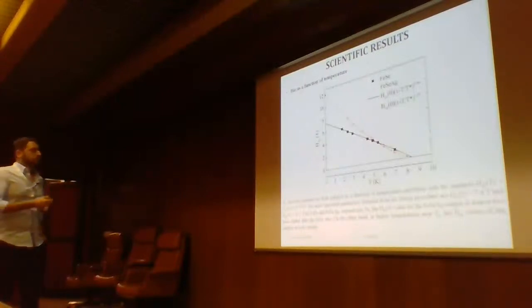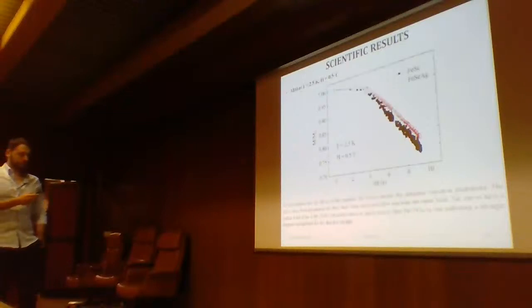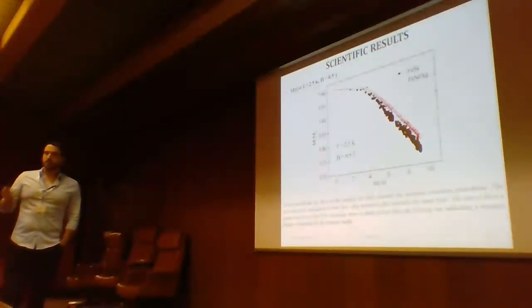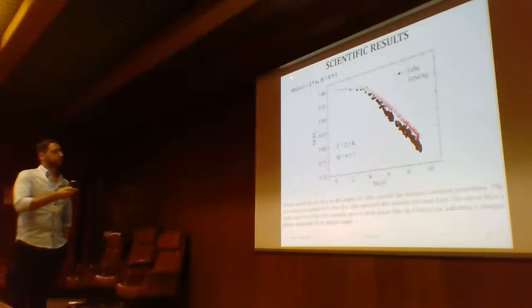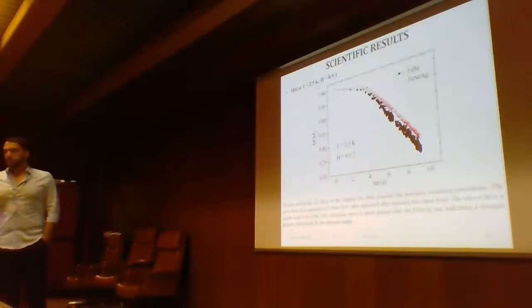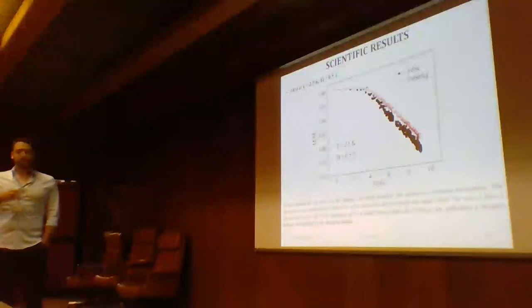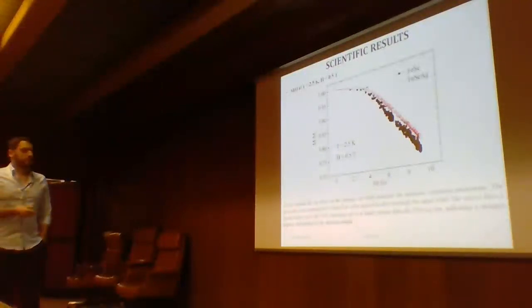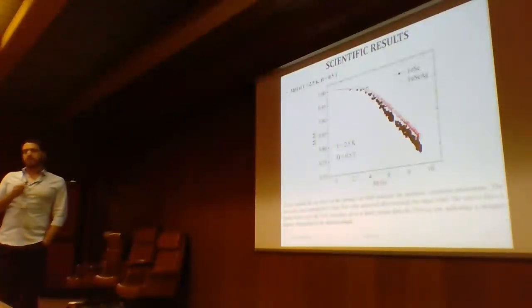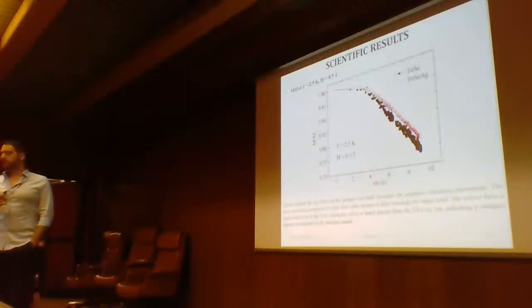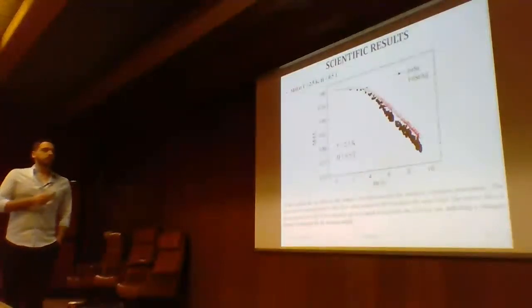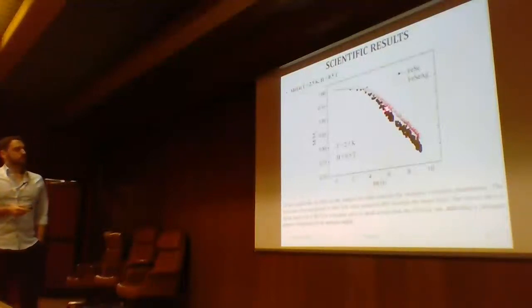you have that this silver doped sample is better in the irreversibility field values with respect to the undoped sample. Now, we can extract another characteristic from magnetization measurements. In particular, if you consider your magnetization as a function of time, you can study the so-called magnetic relaxation phenomena of the sample. This is very important because by means of this measurement, you can extract the pinning energy values of your sample. In this curve that shows the magnetic relaxation phenomenon, you can see how the undoped relaxation curve is much noisier than the silver doped one.